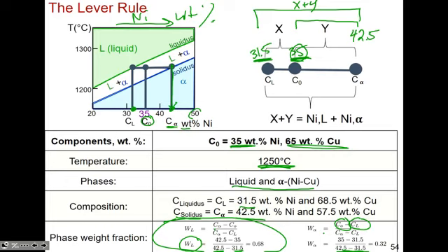So in this instance, if we would have gone with the 65% weight of copper and just moved the lever over to 65% at 1250 degrees, it would have just been all solid. No, you would be at the same place. It's just that your phase diagram is going to be the mirror. You're changing your x-axis now. Yes, so you have to flip all the other values as well. I just worked with nickel, see?